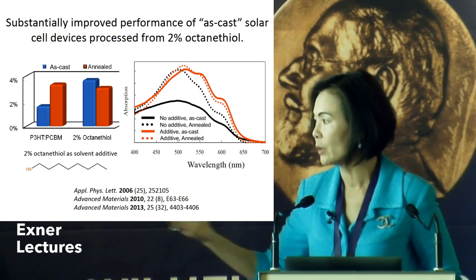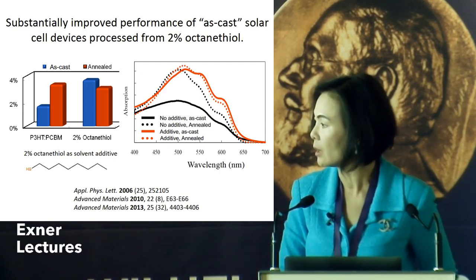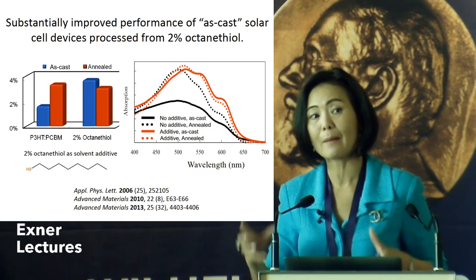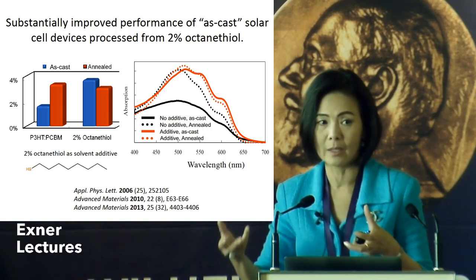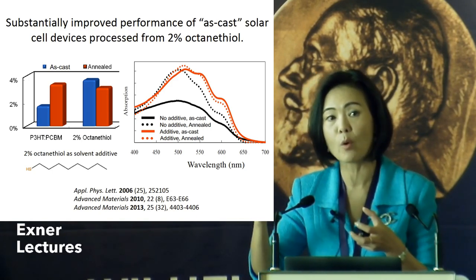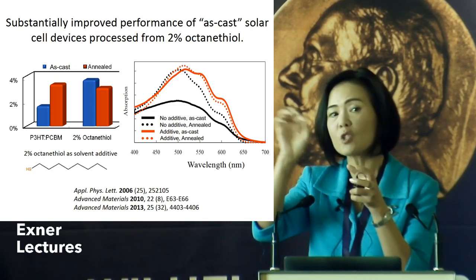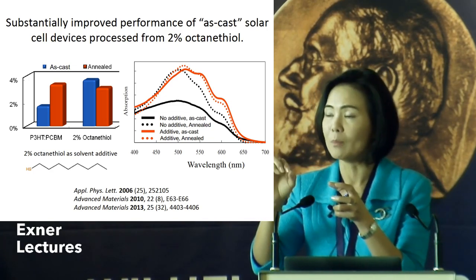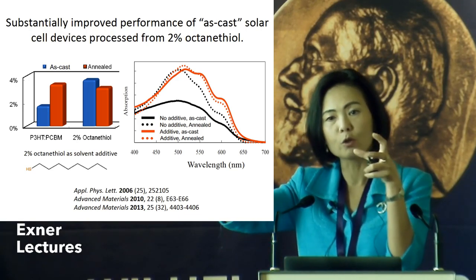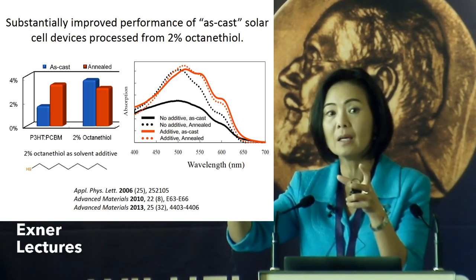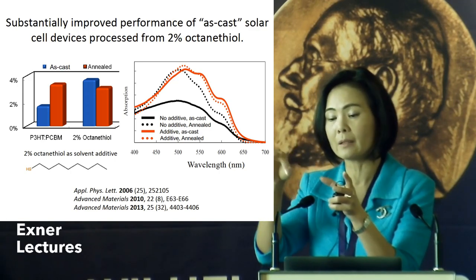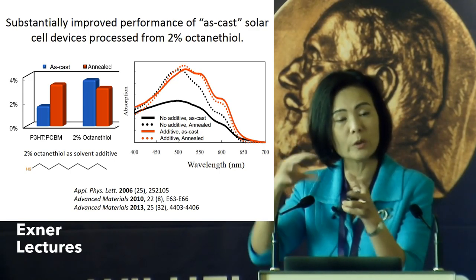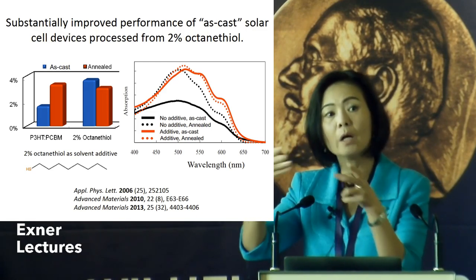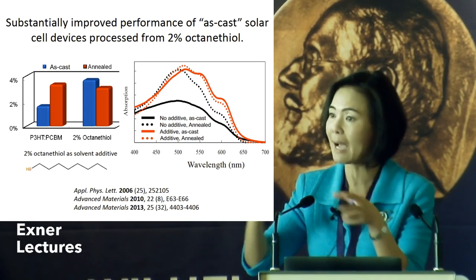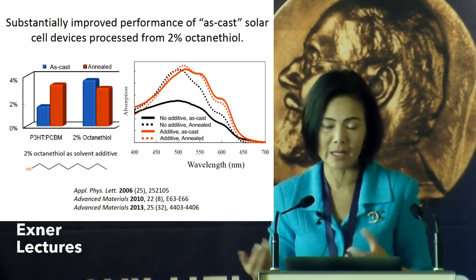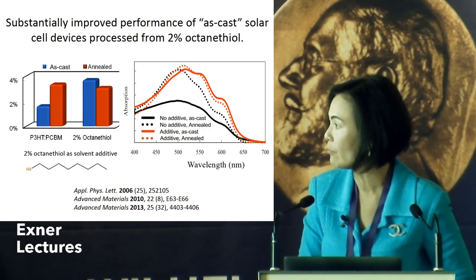And then together with Guy Bazan and other collaborators, we spent a lot of time to understand how the additive worked. So basically, the additive is a high boiling point solvent. And so you add a very small amount, 2% by volume, but as the film dries out, the whole solvent evaporated. So basically 2% at the molecular level is quite a lot. So enough to really slow down the drying process of the film, that allows you to control the film morphology, and therefore you have a better device performance.